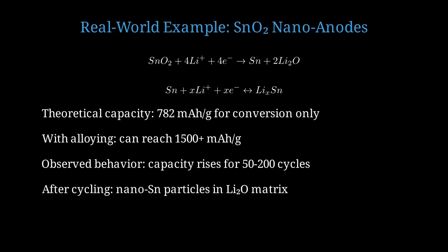Researchers have observed that in nano-sized tin oxide, capacity rises for the first 50 to 200 cycles, often reaching values well above the initial discharge. After many cycles, the material transforms into a composite of tin nanoparticles embedded in a lithium oxide matrix. This nanocomposite is actually more electrochemically active than the original material. This behavior is also seen in silicon anodes, which are being developed for next-generation lithium-ion batteries.